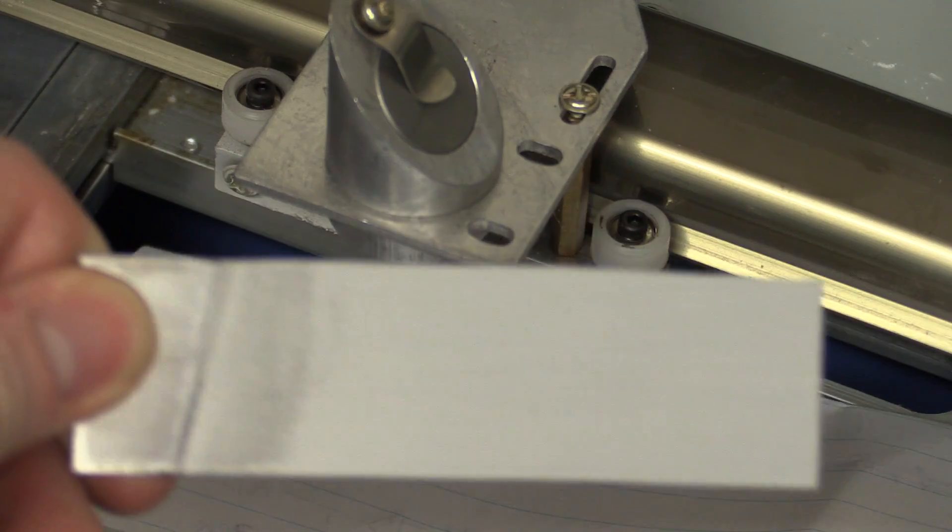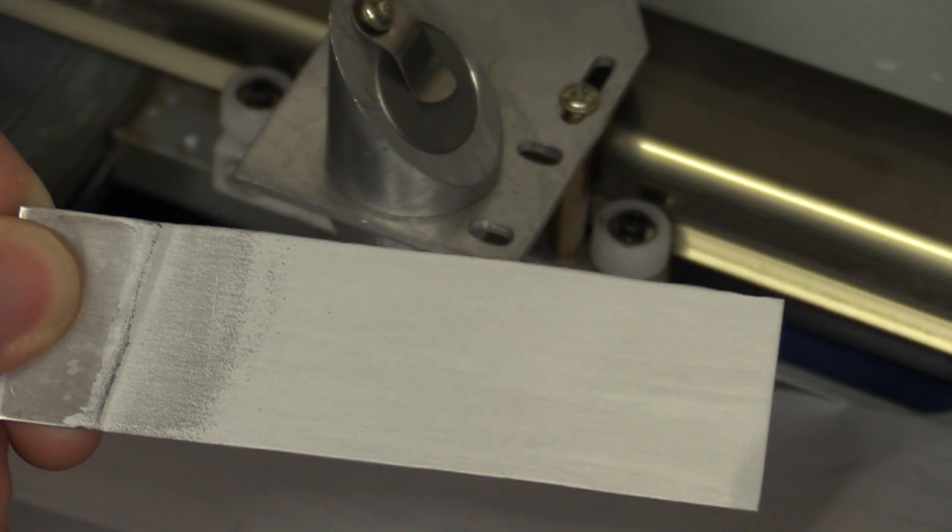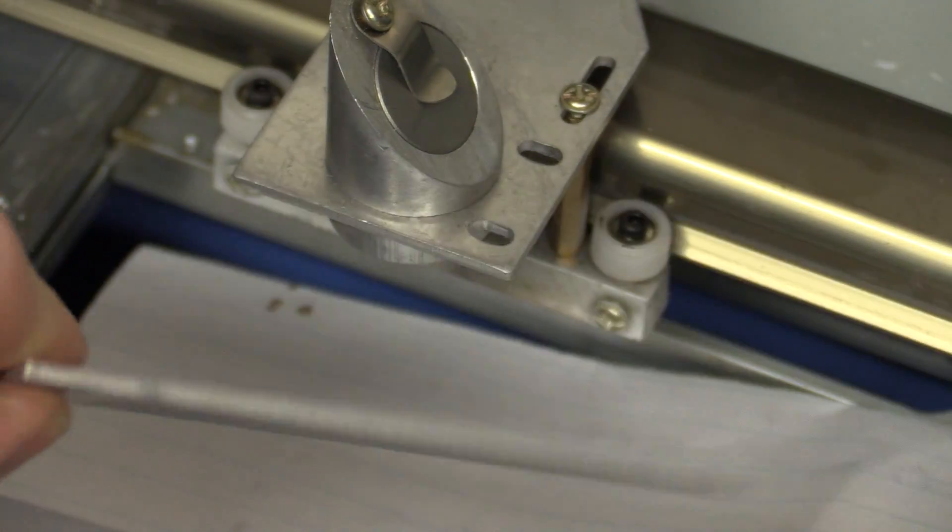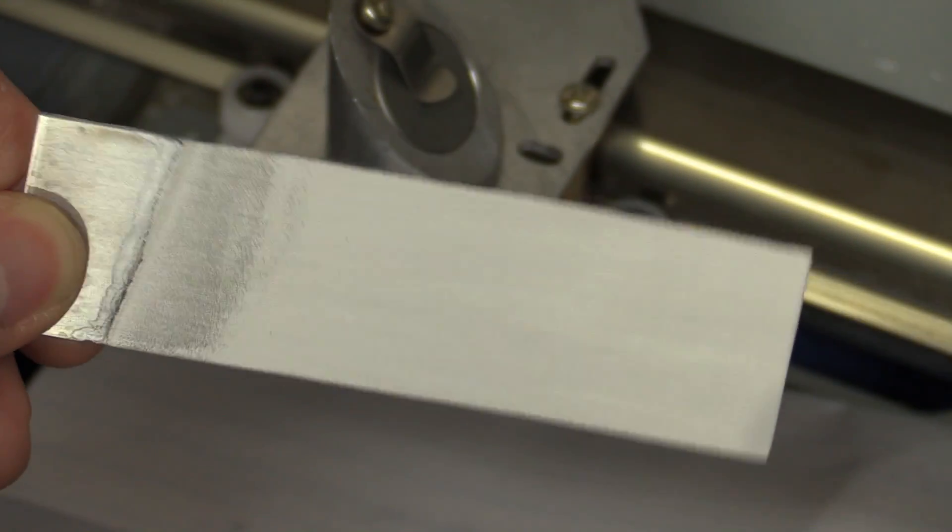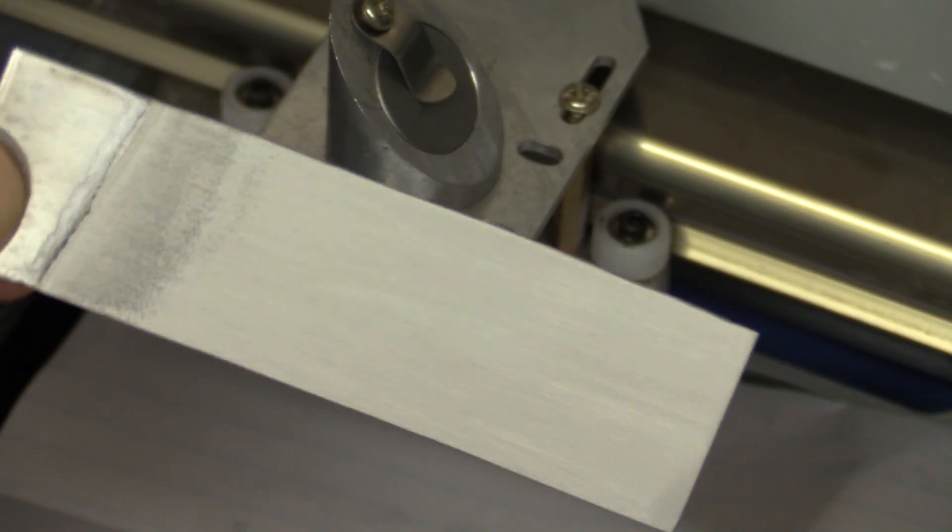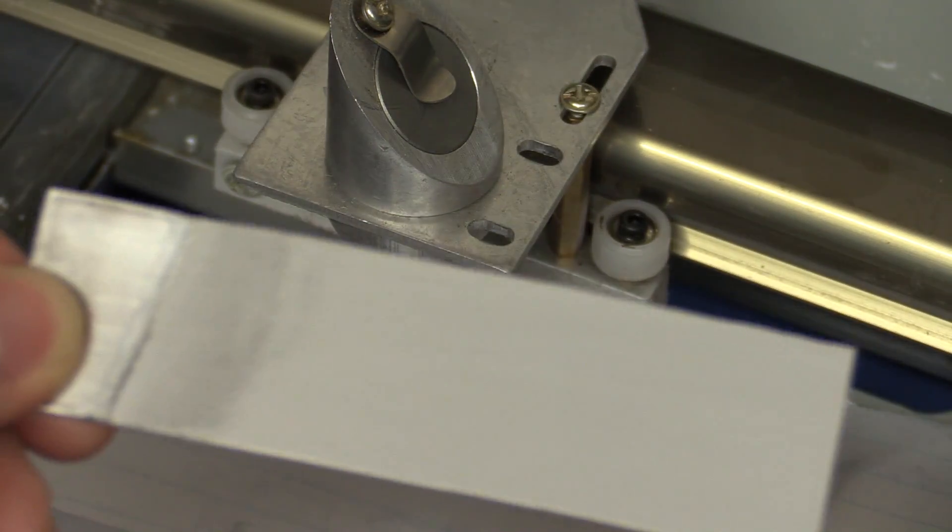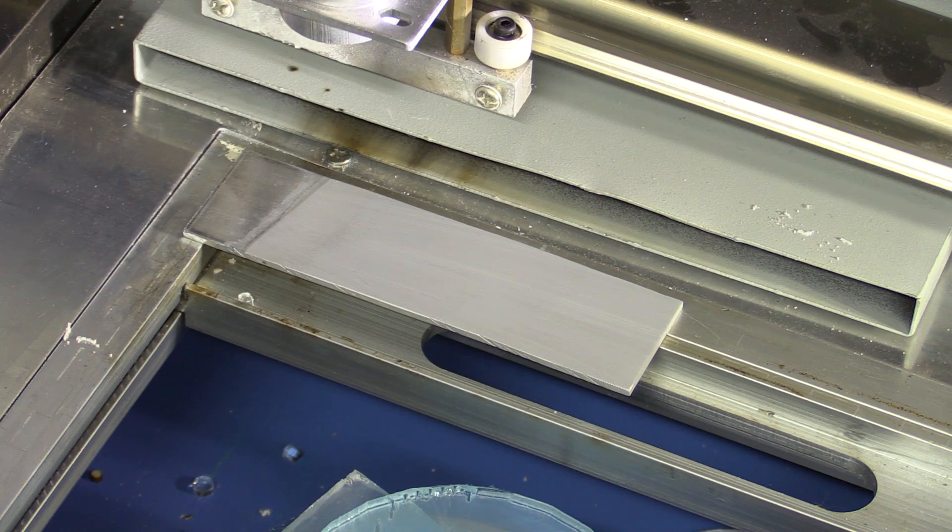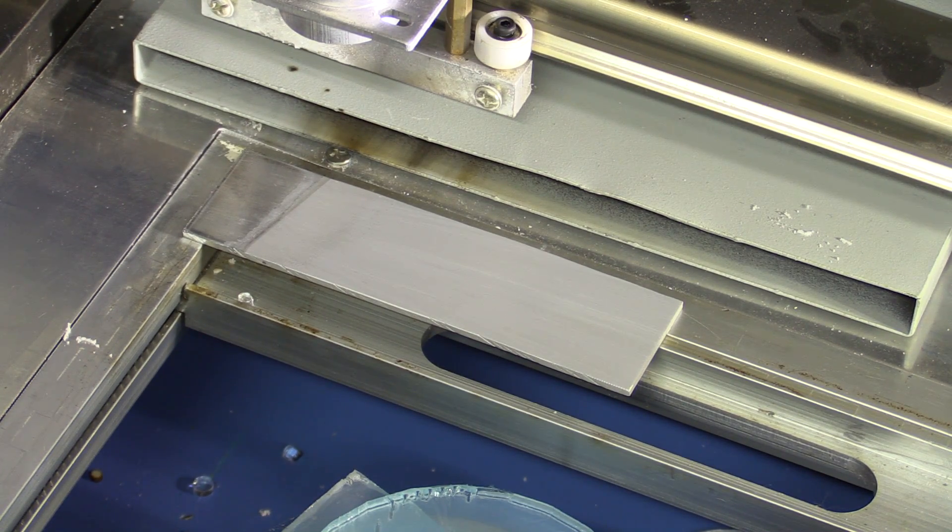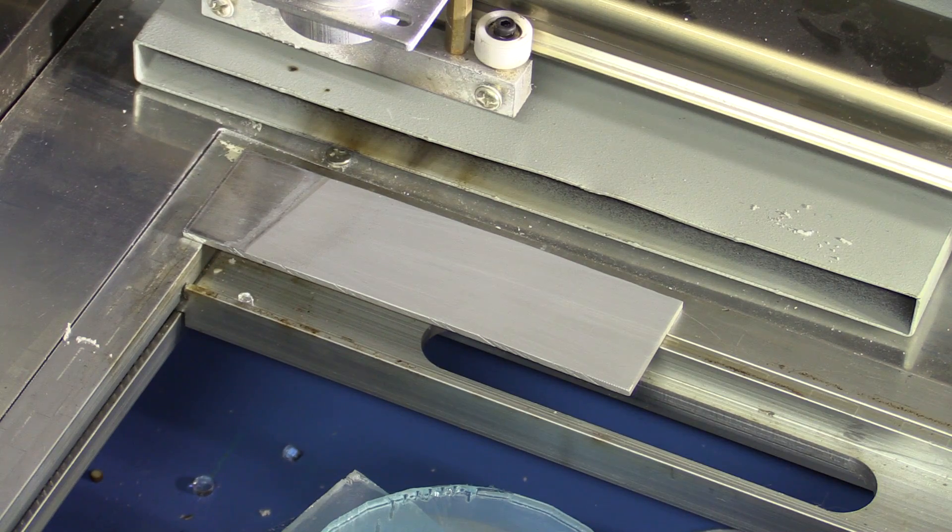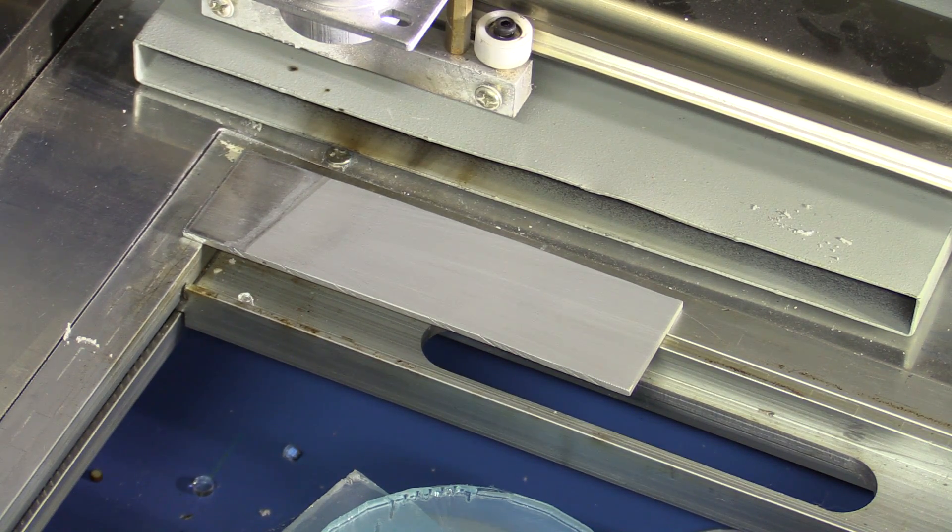I want to give the uncolored another try, so I went and anodized a piece of aluminum myself. So I am sure this is not treated or coated with anything, so let's try that. So I just bumped up the speed a little bit and lowered the power by 10%. It was at 80% before, and now we are doing 70%.